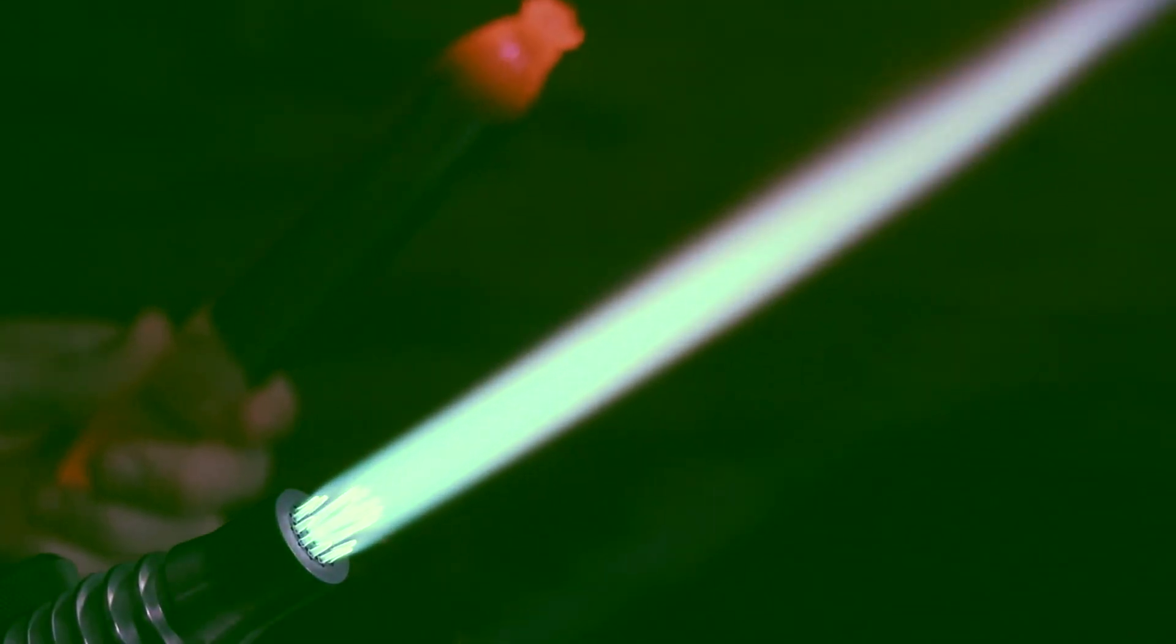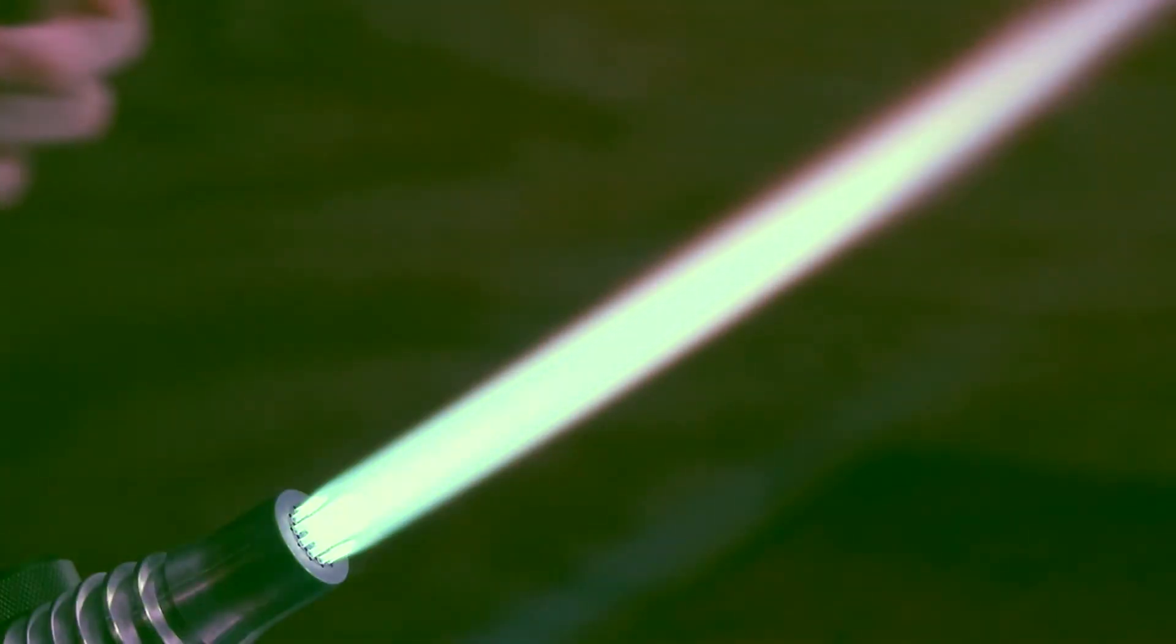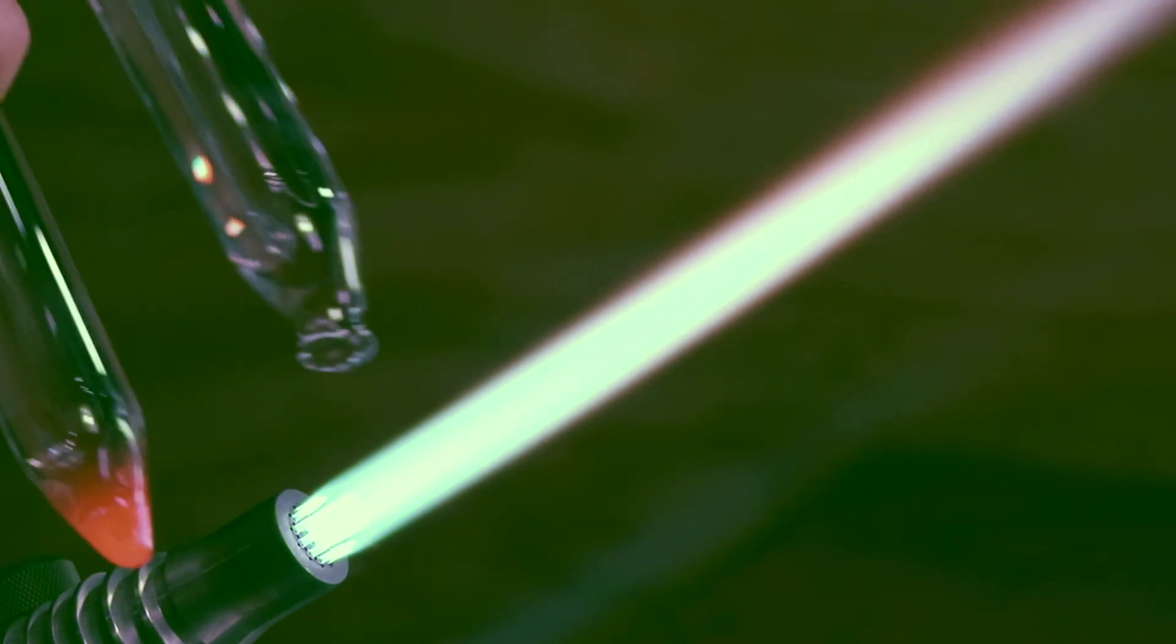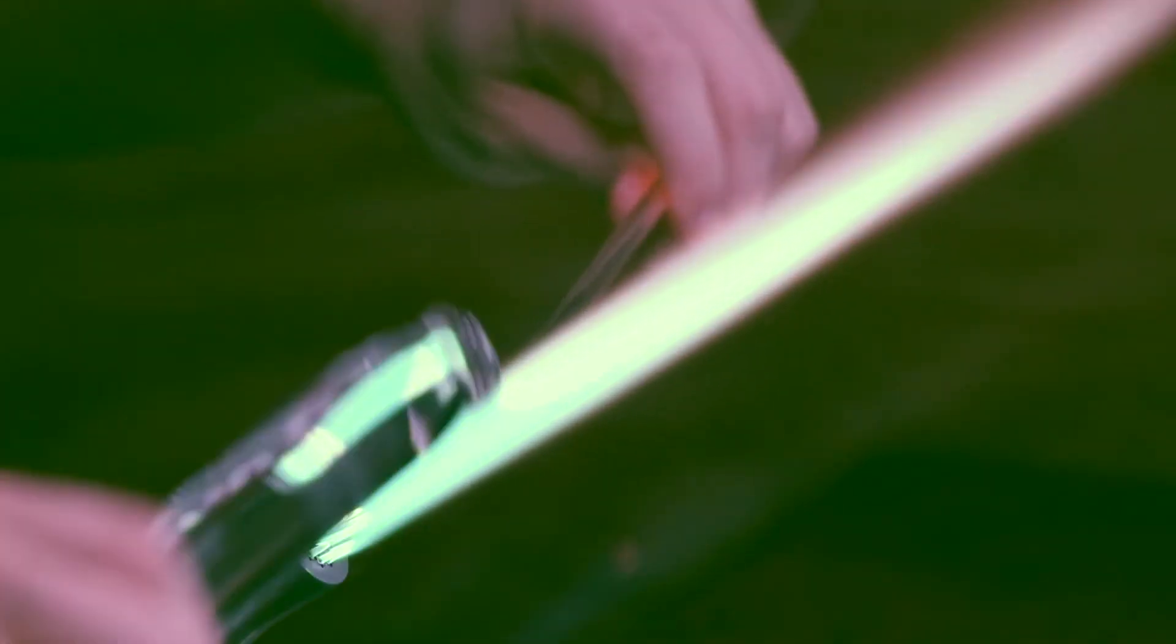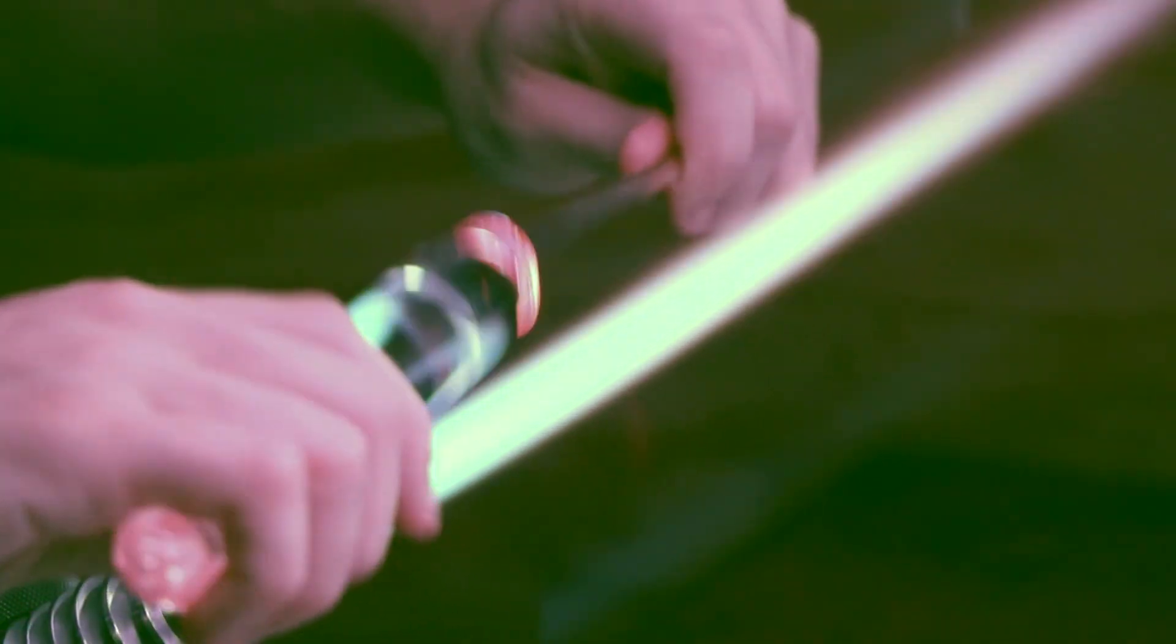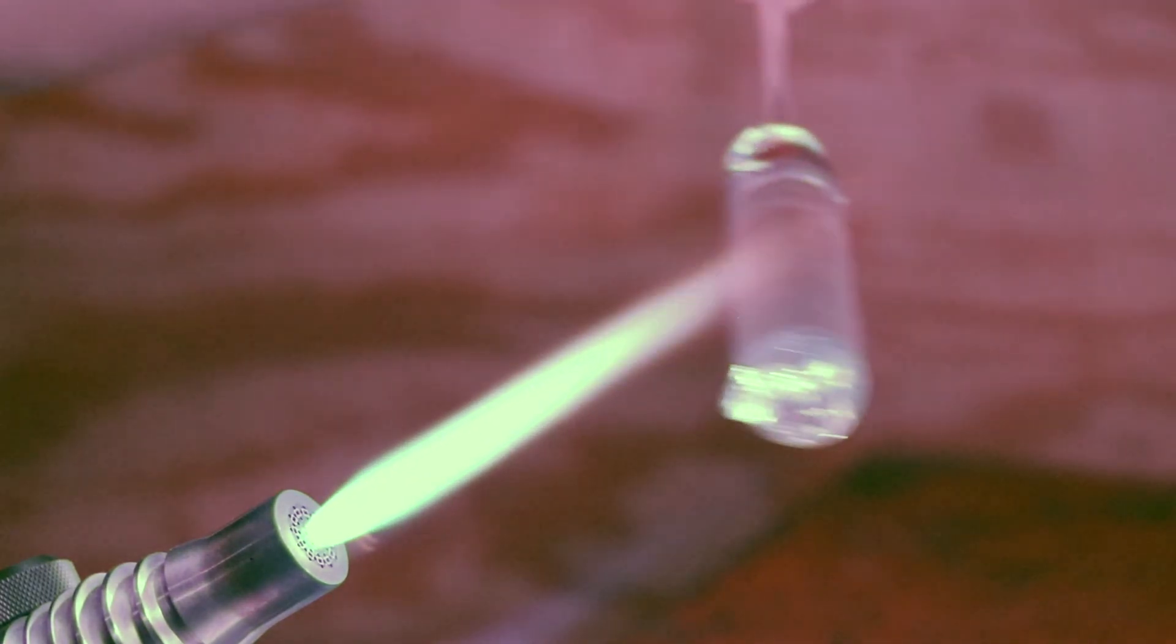It's going to be pretty simple. I just got a one inch rod, solid all the way through, pretty heavy compared to the tube but the same diameter. I went ahead and heated it up and cut it in half. One thing that really helps, especially for later, is you want to heat up the end and get it into a nice point. That's just so when I work on it later I'll heat that tip up, and that's usually the attachment point anyway. It'll radiate the heat back without shocking the rod too much. There's an example of the thermal shock I keep talking about.